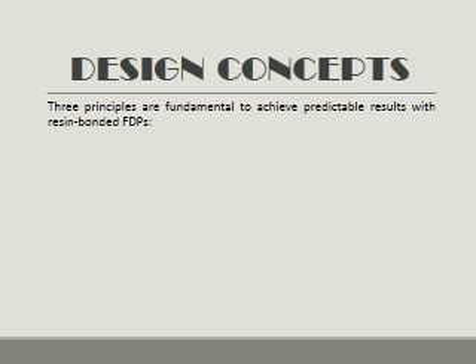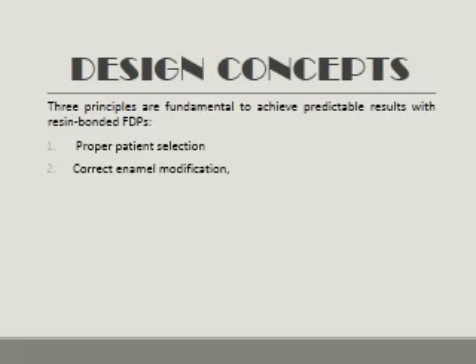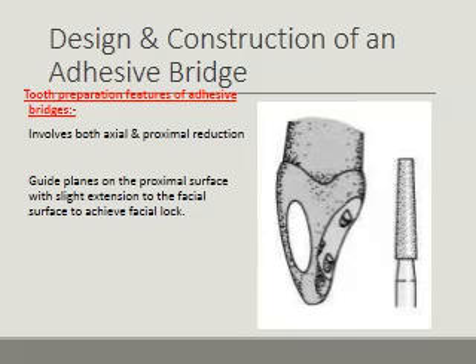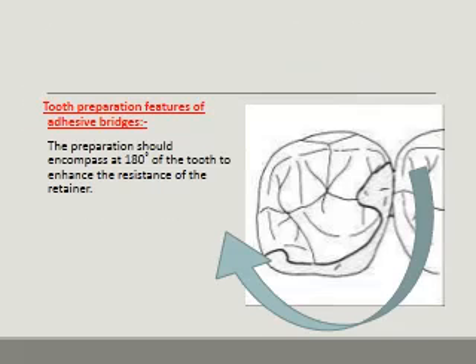Three principles are fundamental to achieve predictable results with resin-bonded fixed partial dentures. These include proper patient selection, correct enamel modifications, and framework design. All these are very important for longevity of the resin-bonded bridge. Preparation of the abutment teeth. Tooth preparation for adhesive bridges involves both axial and proximal reductions. Guide planes on the proximal surface with a slight extension to the facial surface to achieve a facial lock. The preparation should encompass 180 degrees of the tooth to enhance the resistance of the retainers. As I said previously, maximum wraparound is very important for good retention.